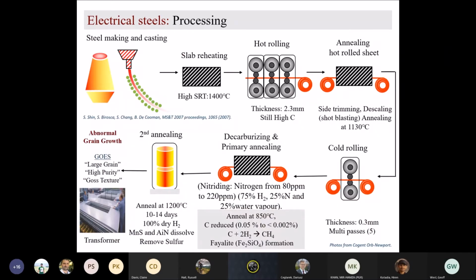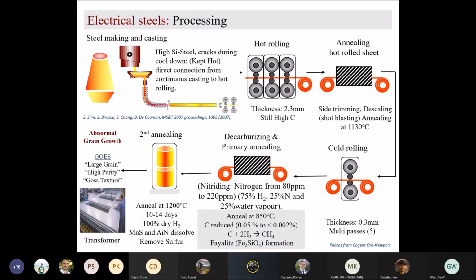So here we have how the processing happens for electrical steel, starting from conventional steel making and casting, then slab reheating at 1400 at some companies, then hot rolling. However, this has changed in most companies these days, because after continuous casting, if you let it cool down, the steel will crack. That's why we want to keep it hot and connect it directly to the hot rolling mills.